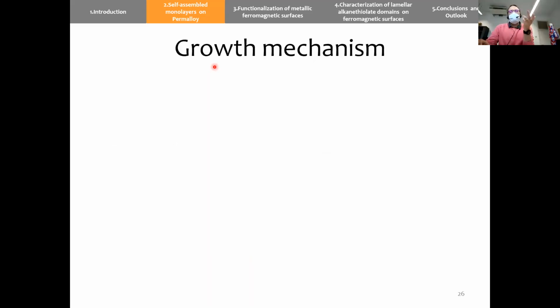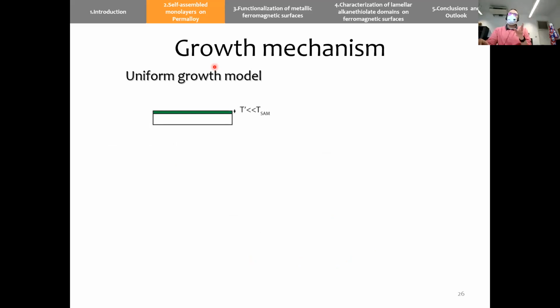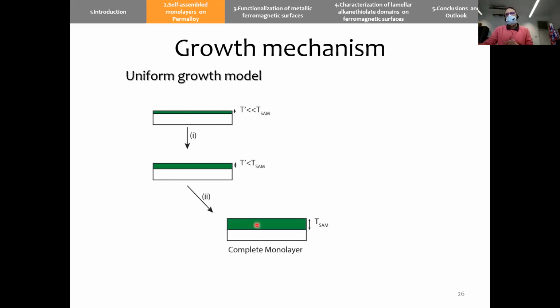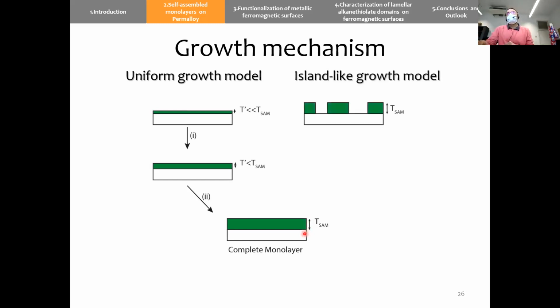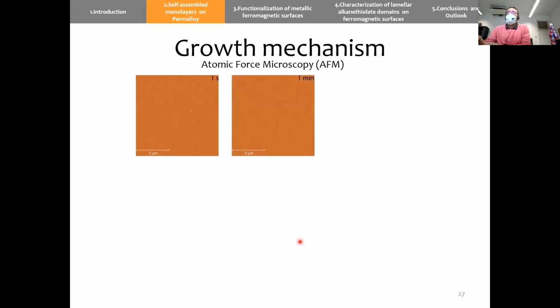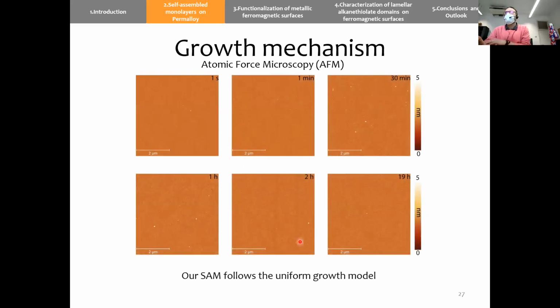For this kind of SAM, two models were described in the literature. The uniform growth model, where the molecules first reach the substrate surface, and then start arranging until the final packing is achieved, and until the final thickness matches the theoretical one. Or the island-like growth model, where patches of the SAM are formed, and then there is coalescence until the complete monolayer is formed. We observe in our case that we are in the uniform growth model, because we don't observe any patches during this kinetic study.